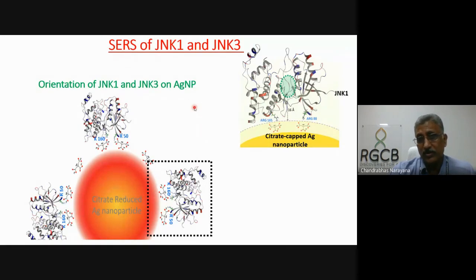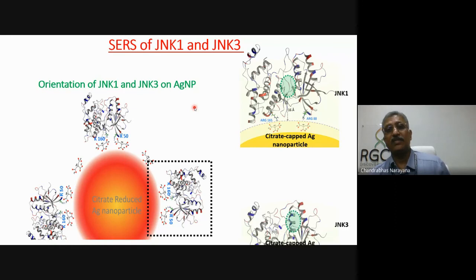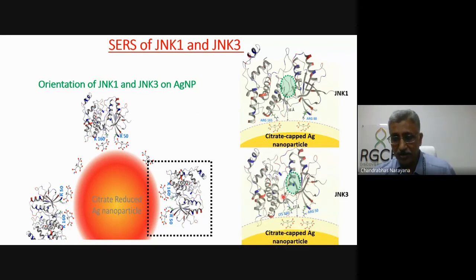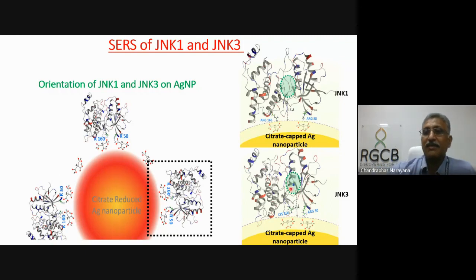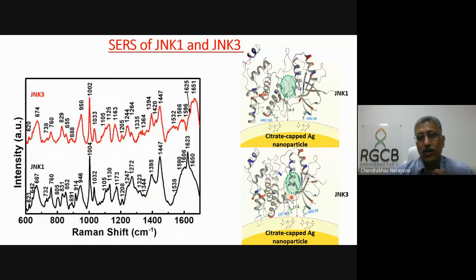So what we wanted to know is whether we can quickly look at the screening of these molecules. We understood that the molecule is binding to this region, and this region happens to be within 1.7 nanometers. Naturally, this is an organic molecule and this is a protein. Though the organic molecule is insoluble in water and the silver is in aqueous solution, since it gets localized here, we know that the organic molecular signature will be much higher. If this is bound well, the signal of the system will be much more. So we did the JNK1 and JNK3 protein spectra.